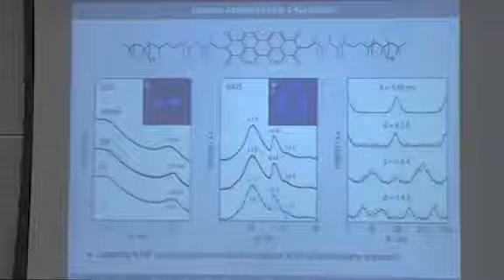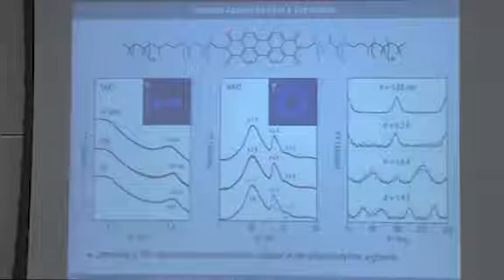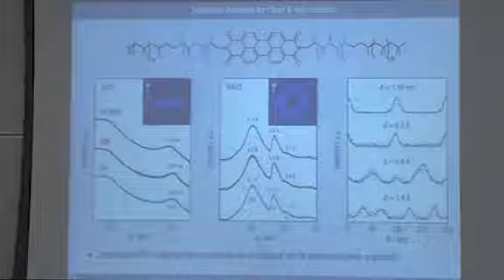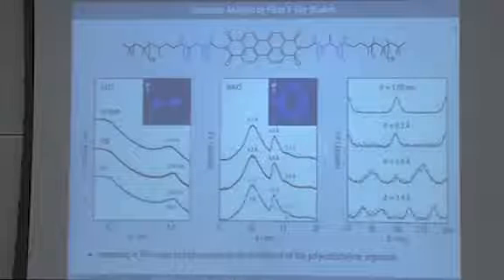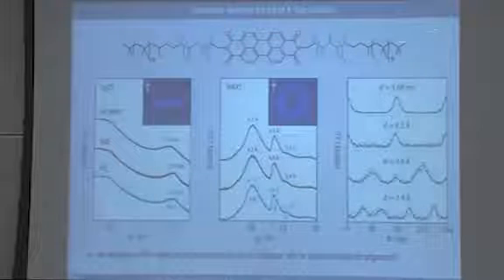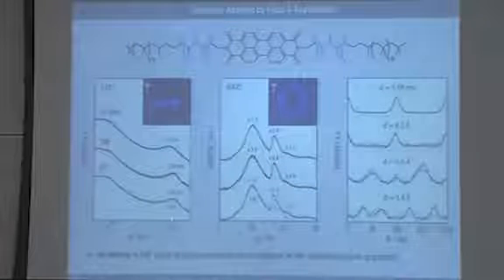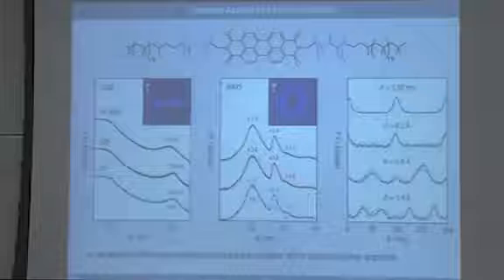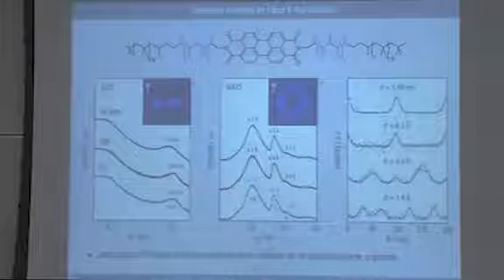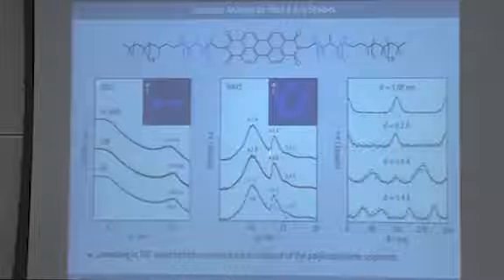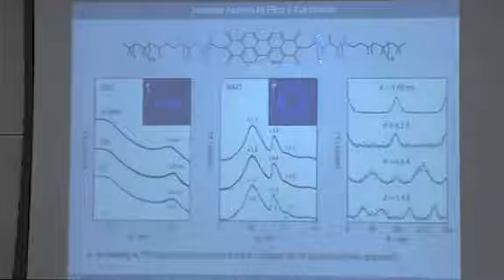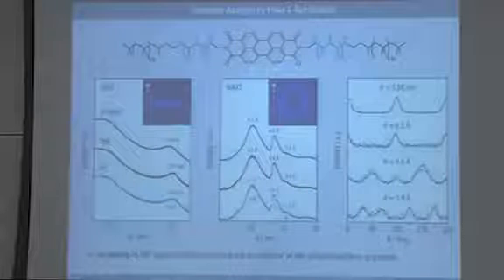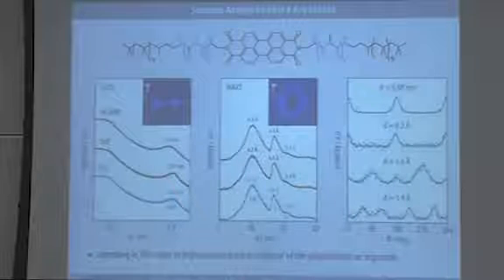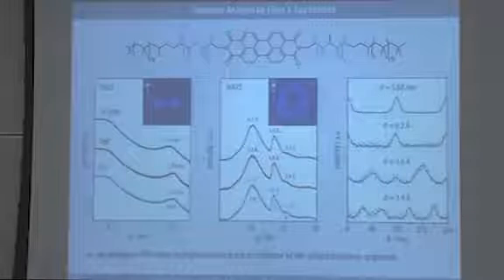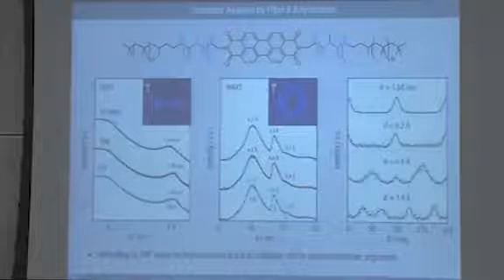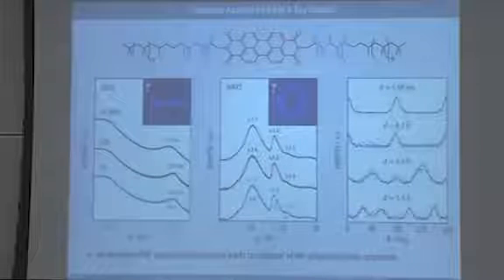However, more importantly, these microfibers then allowed us to do fiber X-ray. And here you can see, in the small and wide angle X-ray region, mainly 4 peaks. The least important one is the biggest one, which is just the near order peak of the attached polyisobutylenes in this case. But then you see a 6 nanometer peak, which corresponds to the diameter of the closely packed nanofibrils. You see a 4.6 angstrom peak, which is a little smaller, I have to say, than the typical intermolecular distance in beta sheet-like systems of oligopeptides. And you see the 3.4 angstrom peak that one can assign to the pi-pi stacking inside the nanofibril.